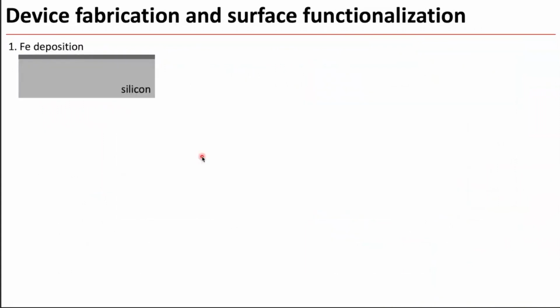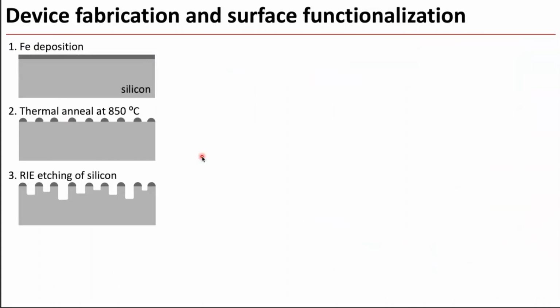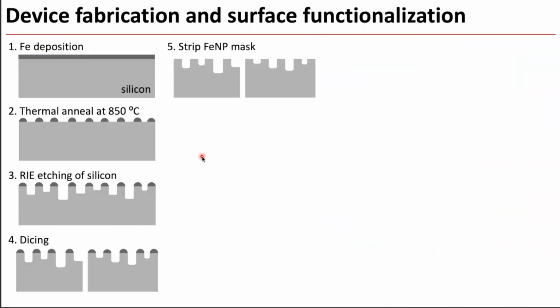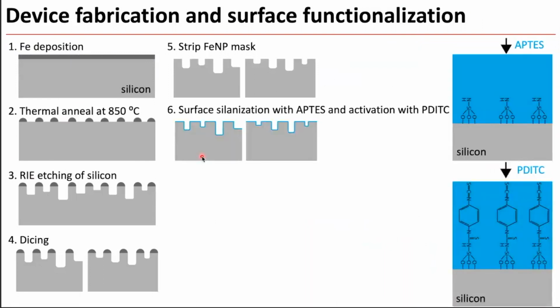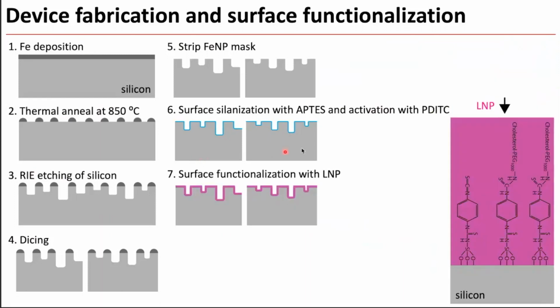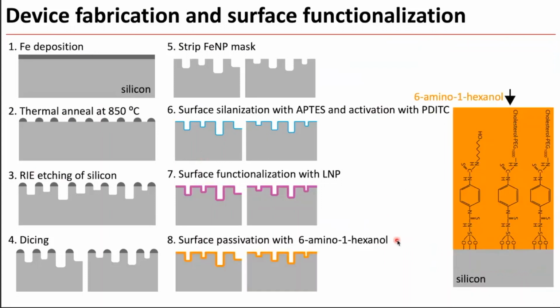So this is the fabrication process. We deposit iron, and then we do thermal annealing. We run RIE etching, and then we dice the wafer. We remove the etching mask, and then we start to do surface functionalization. The first step is silanization, and then we functionalize the surface with the lipid nanoprobe. So in this case, we don't have the second molecule, which is the capture probe. We directly functionalize the lipid nanoprobe on the surface. And then finally, we passivate the surface to minimize non-specific binding.